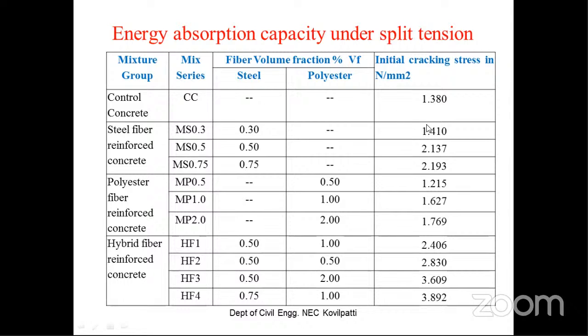So you can see the initial cracking stress under split tension loading condition. The last four rows, obviously, are the hybrid fiber series. The split tensile stresses are in the range of 2.4 to 3.82, whereas the control concrete is 1.3 and steel fiber is 2.1. And in polyester fiber, it is in the range of 1.2 to 1.7.